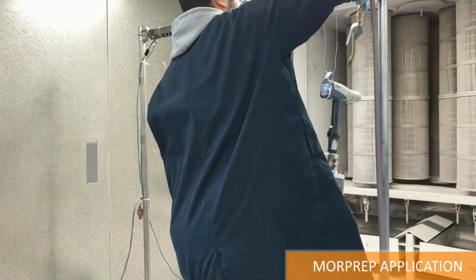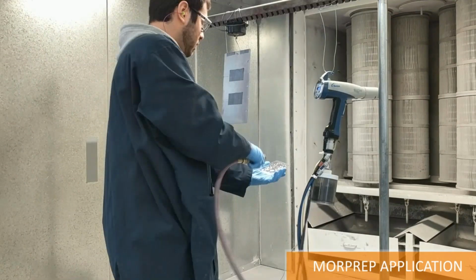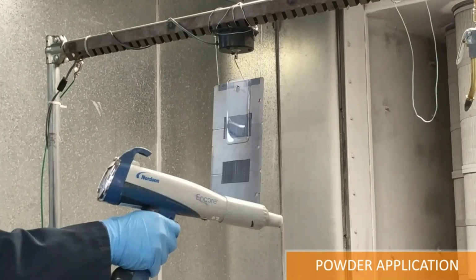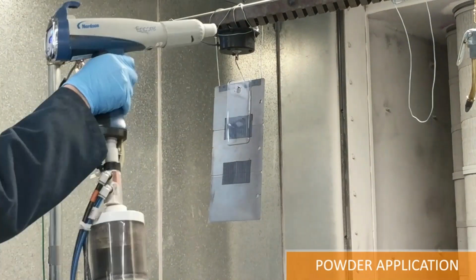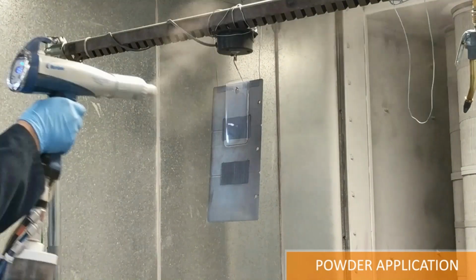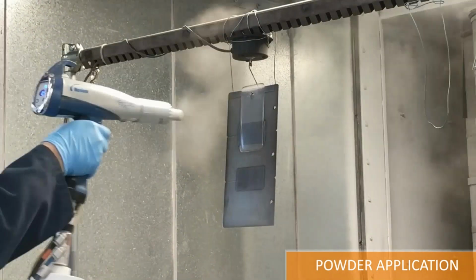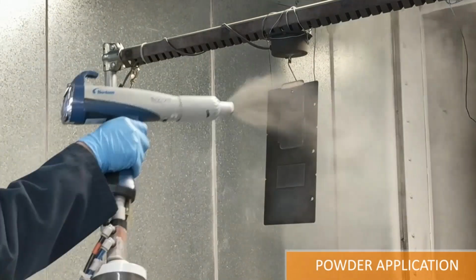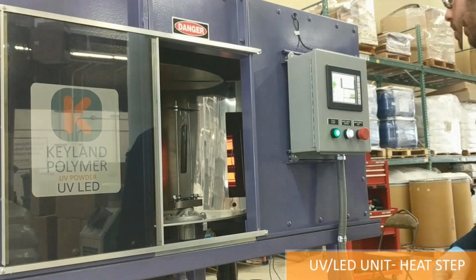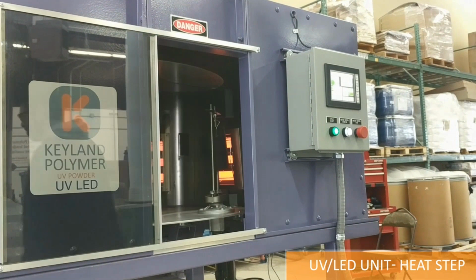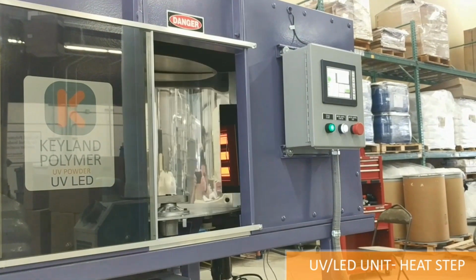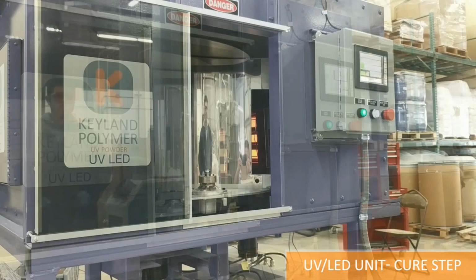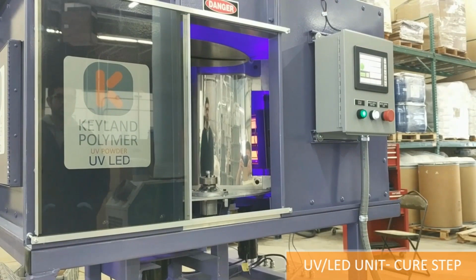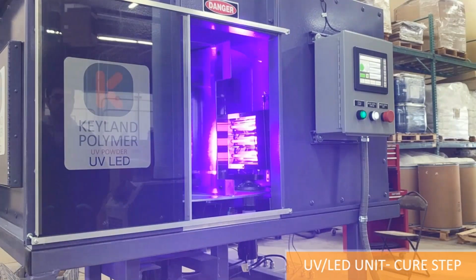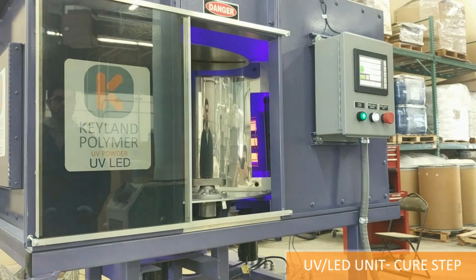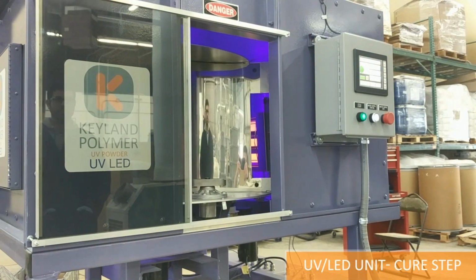Now here's the conductive primer being applied and removed with compressed air. These materials can be either water, alcohol, or solvent-based. There's the electrostatic deposition of the powder onto the part. And then here we fondly name this Barney, and the part you'll see is going into its melt stage, approximately 1 minute. And after that, it's followed by UV, and in this example, it's UV LED for cure.